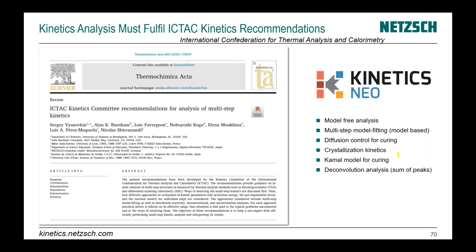Thank you very much. The next question: what are the advantages of integral methods over the Friedman method for activation energy determination? I would say disadvantages first. As I showed, integral methods have influence from previous steps on the last steps, and therefore the last steps are not well described. That is the disadvantage. From advantages, integral methods may give more stable results for activation energy. But you must take into account that there should be not a very complex reaction — maybe for single-step reactions, integral methods work better than the differential methods like Friedman. Because Friedman has a more noisy result and integral methods have a more stable result, but again it works for single-step reactions or reactions where the activation energy changes very slowly and very little.